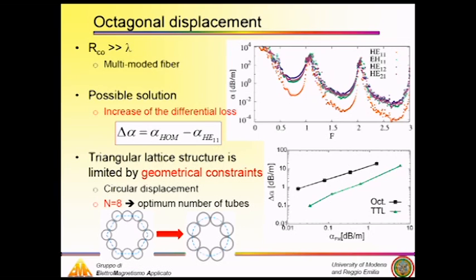A possible solution to reduce the effect of these high-order modes is to increase their losses with respect to the fundamental one. Due to geometrical constraints, it is very hard to accomplish this in the triangular lattice shown before. So we decided to change this geometry to the circular case. That's due also to the fact that the confinement mechanism does not rely on the particular arrangement of the tubes, but simply on the spectral properties of the tube itself.